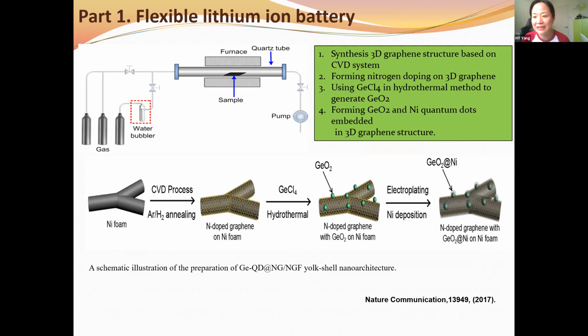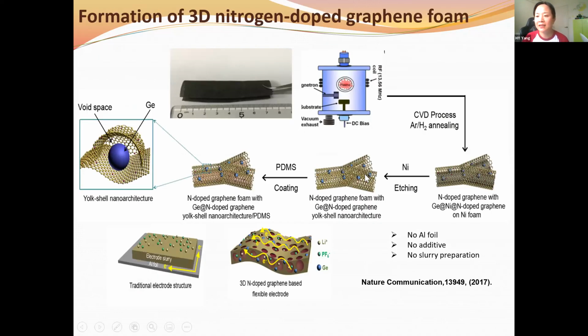So I want to give a few examples today. One example is that we synthesized nanoparticles combined with a three-dimensional graphene system for flexible lithium-ion batteries. We utilize a chemical vapor deposition, CVD, system to generate graphene and three-dimensional graphene. After the three-dimensional graphene is synthesized, we dope it with germanium oxide and nickel nanoparticles. Then we coat another layer of graphene oxide, nitrogen-doped graphene. So we have two layers of nitrogen-doped graphene with nickel nanoparticles in the middle, and further reduction will generate nickel metal nanoparticles, forming a three-dimensional electrode for these lithium-ion batteries.